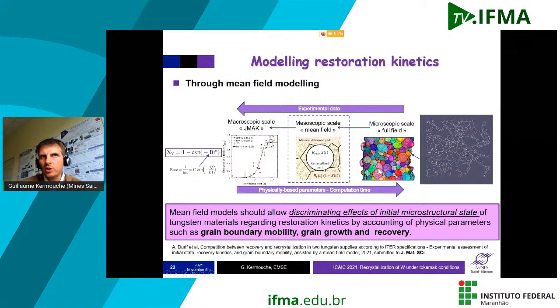And so we try to model each grain separately and we let the recrystallization happen. So here the computation time is very costly. Here it's very rapid, but you need a lot of experiments. In between, there is some mean field modeling that we use. Finally, that considers each grain separately, but you don't need to model all the grains because a grain is related to what happened to the average microstructure. Okay, so we use some physical parameters here, but the computation time is quite low.